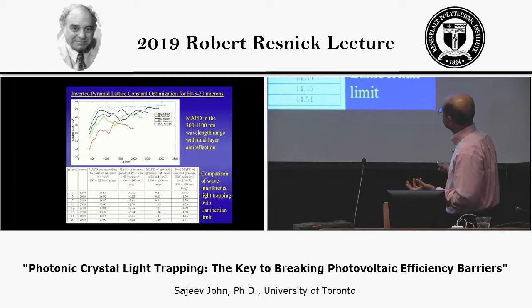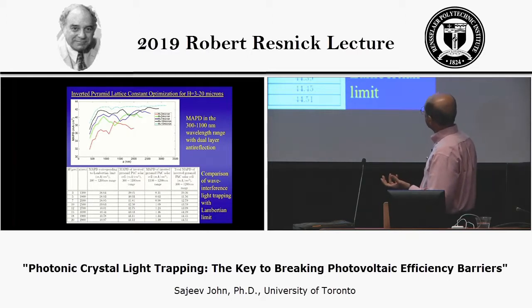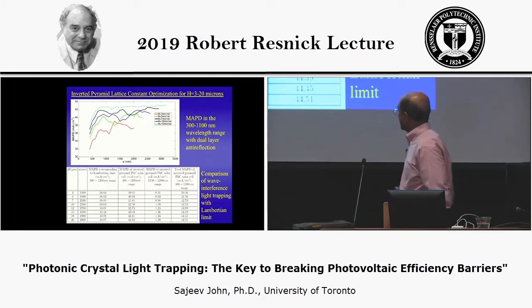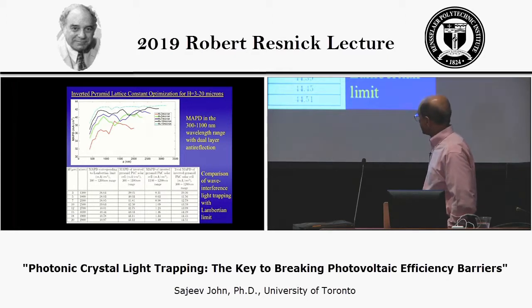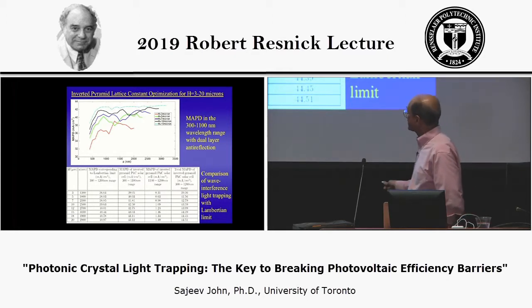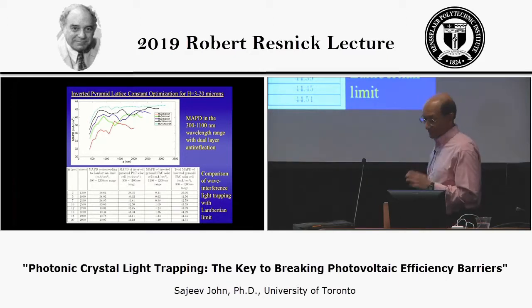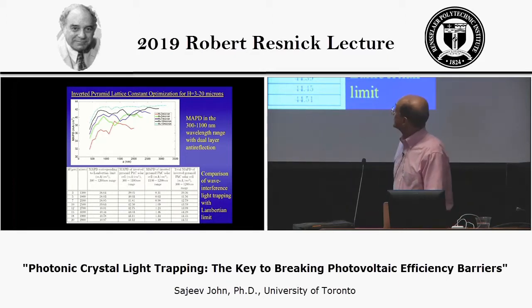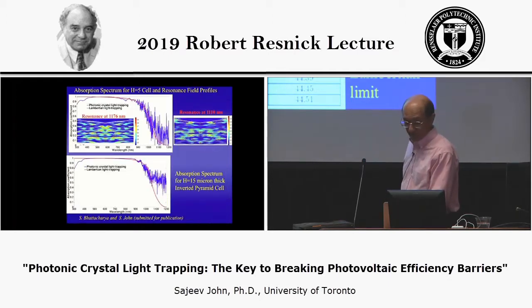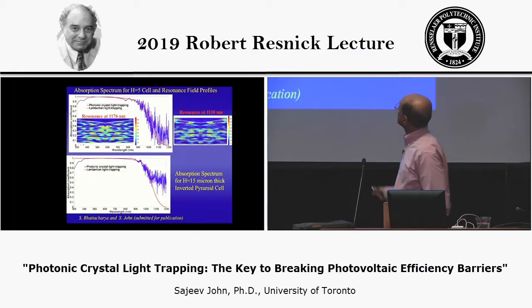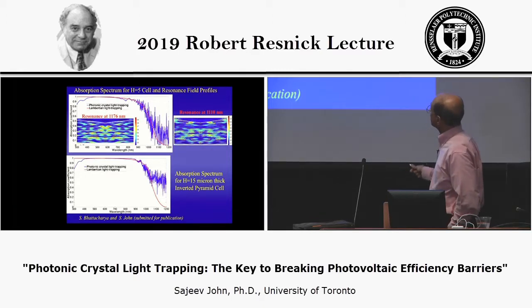So when we add the two together and look at 300 to 1200 nanometers, in some cases we're close to 3.5 to 4 milliamps above the Lambertian limit. And that is what really allows us to reduce the bulk Auger recombination losses and go to a much thinner cell. So here again you see some of the optical spectra. This is for a 5 micron thick cell.